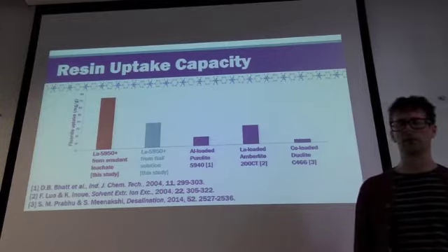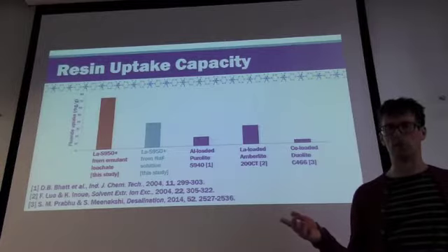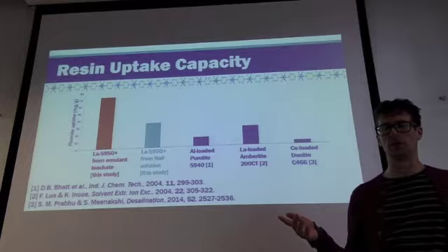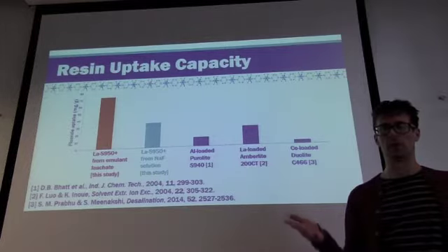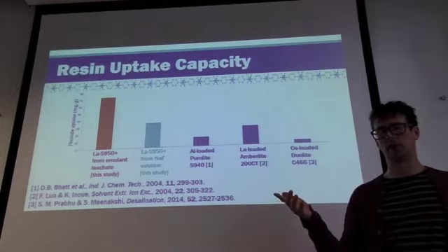And what we can see from this is that not only does our resin outperform what was previously reported in the literature on a level playing field, but also, and more interestingly, we get this very considerable enhancement effect when we try to extract fluoride from the emulant SPL leachate.